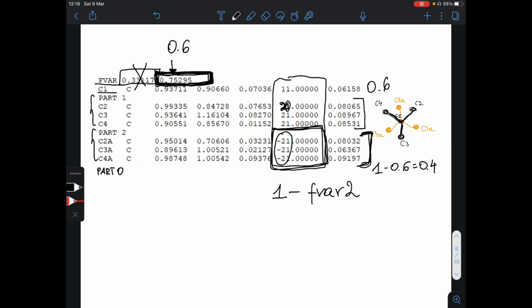If at some point we had another disorder in the ins file, then we would again have part 1, some atoms, part 2, some atoms, part 0, and then we would relate that disorder to the third free variable. For part 1, we would write 31.